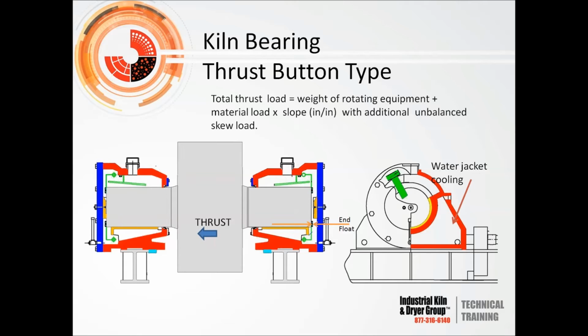One thing unique about these bearings too is, like Roland said, it's a 180-degree bearing, so that means that the bearing liner is actually offset to the angle between the rollers and the tire. So it's very important that you hold that angle within a couple degrees. If you start getting too far in with your roller or too far out, it can affect how that bearing liner wears. Which is different than a spherical roller bearing, where the angle that the load's applied to it really doesn't make any difference, except if you turn the bearing upside down and have load up the cap.